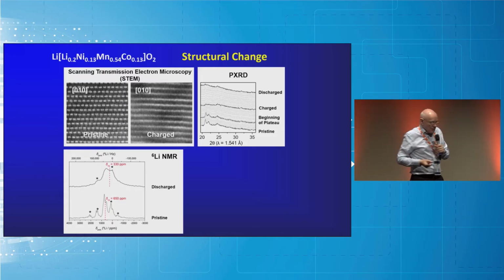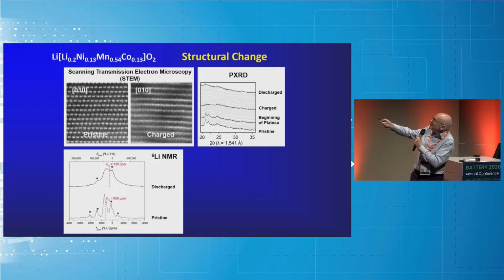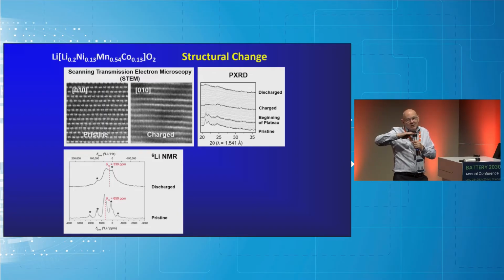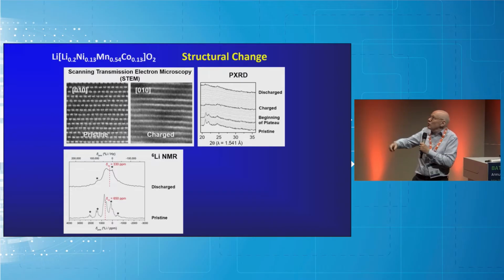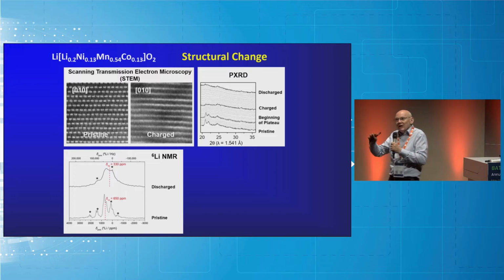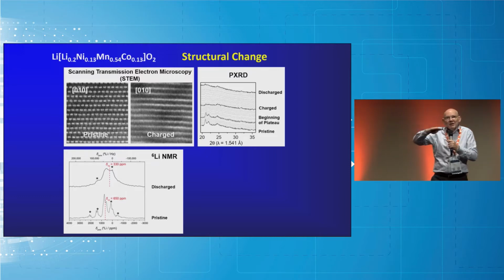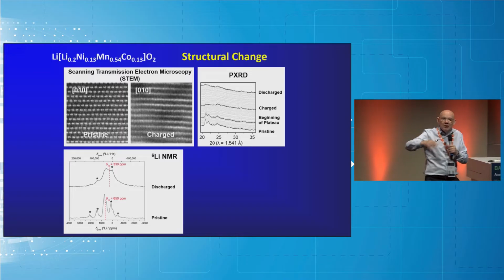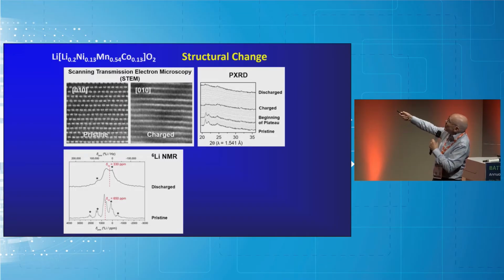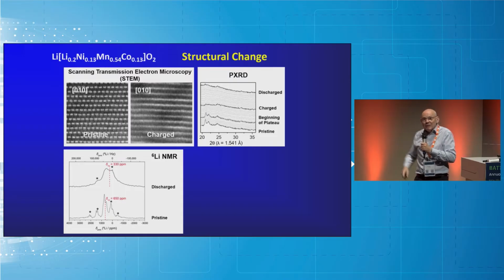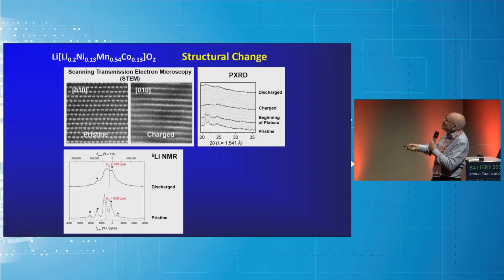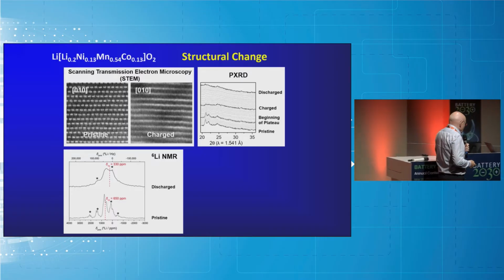However, when we charge the material, that's the second image, this one on the right here, after charging, what you see is the transition metals have disordered in the transition metal layer, principally. So remember, what's happened is we've taken lithium ions out. Some of them have come from the transition metal layers. They've left lithium vacancies. The transition metals now have the possibility of reorganizing, of losing the honeycomb structure, and that's what they're doing here. That's why you get this smearing out of the light scattering. And you've now got this disorder in the transition metal layers. And these two pieces of evidence are just powder diffraction and NMR that confirm the loss of the honeycomb structure.